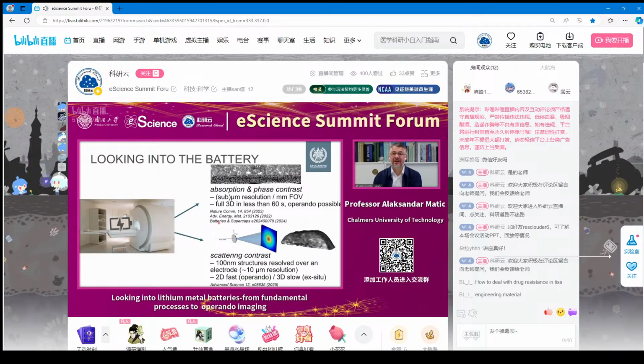And either you can use this type of phase contrast imaging, which is very similar to what you do when you actually go to the doctor. So you create a real image based on the absorption of X-rays by the sample. And here is one example of a graphite electrode, which we studied, and we looked at how it degraded by lithium plating at harsh conditions.